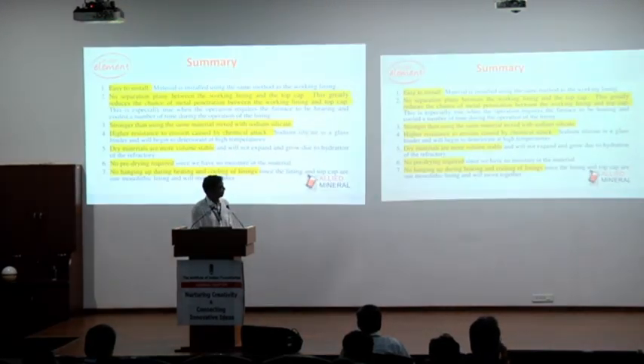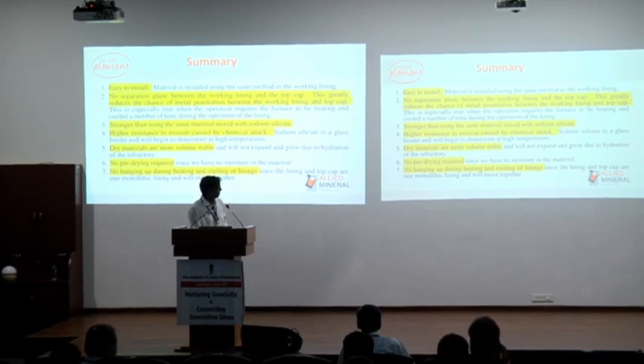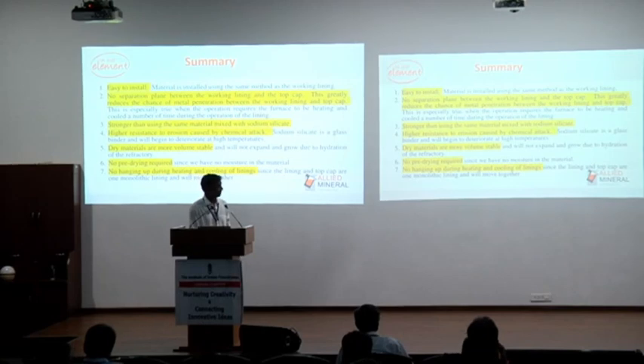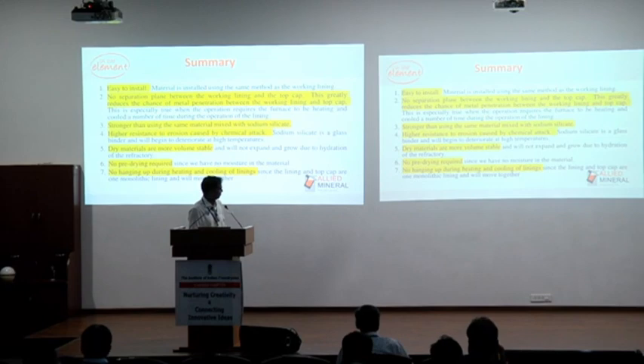To sum up with respect to top caps, it's easy to install. As I said, there's no separation between the main working lining and the top cap, and it reduces the chance of metal penetration between the main working lining and top caps, and it contributes to the safety of the furnace and the safety of the people working around. It is stronger than using the same material mixed with sodium silicate, with higher resistance to erosion caused by chemical attack. It is dry and more volume stable. No preheating is required, and during the expansion and contraction of the lining, there's no hanging up.